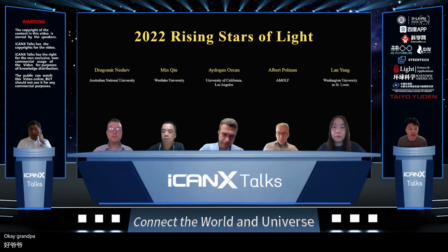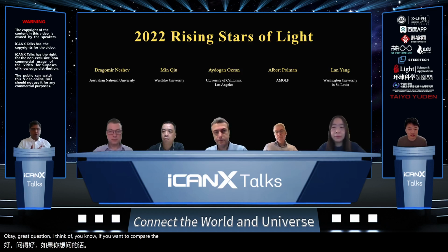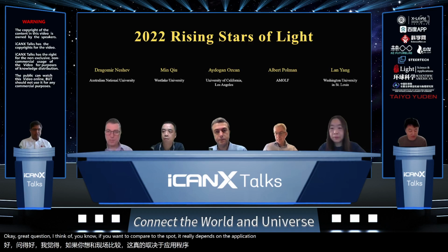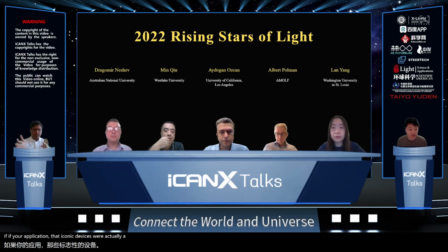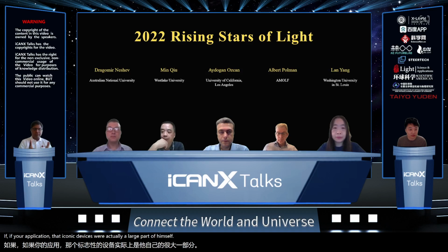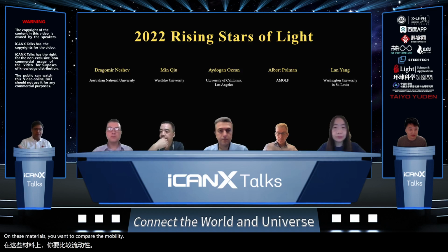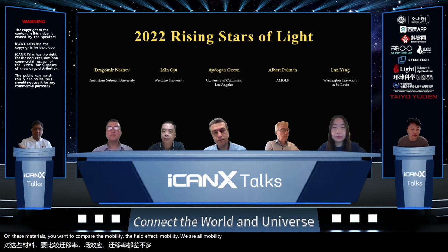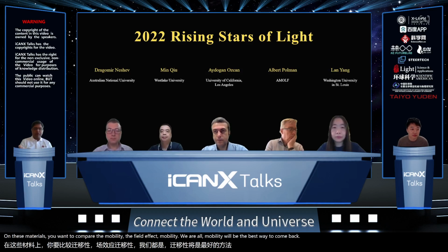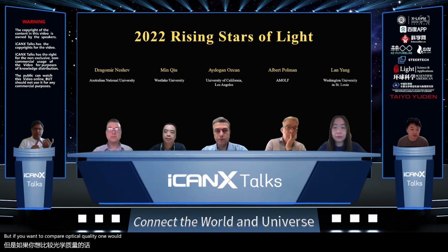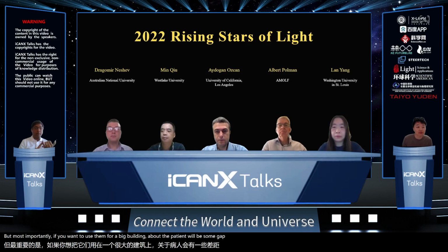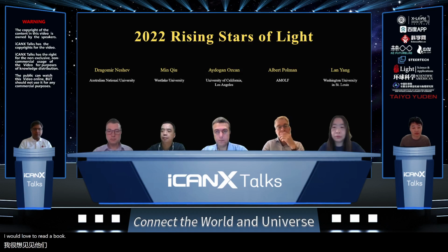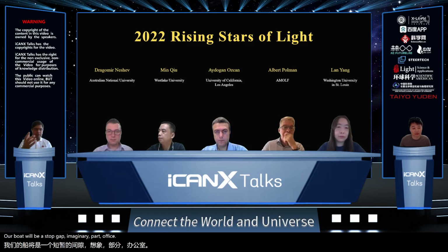Again, great question. If you want to compare this quality, it really depends on the application. If your application is electronic devices, where a large focus of research also is on these materials, you want to compare the mobility. The field effect mobility or Hall mobility would be the best way to compare them. But if you want to compare optical quality, one would be the magnitude of the optical dielectric constants. But most importantly, if you want to use them for a waveguiding application, it would be the sub-gap optical constants. So it's the sub-gap imaginary part of the optical constant, the sub-gap absorption.